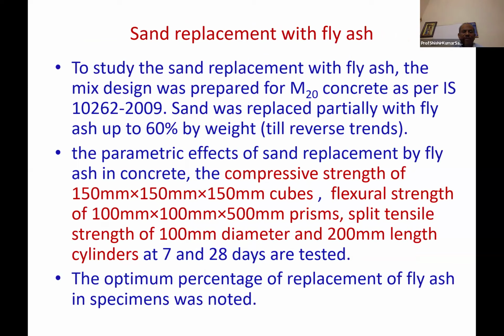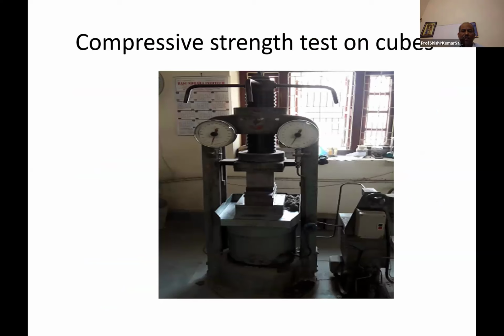Sand replacement. To study the sand replacement with fly ash, mix design was prepared using M20 concrete as per the mix design code 10262. Sand was replaced partially with fly ash up to 60% by weight till the trend reversed. The parametric effect of sand replacement in fly ash concrete we have tested through compressive strength on 150 millimeter cubes, flexural strength on 100 by 100 by 500 millimeter prisms, and split tensile strength on 100 millimeter diameter and 200 millimeter length cylinders, cast and tested at 7 to 28 days. The optimum percentage of replacement of fly ash is noted. This is the compression test machine.